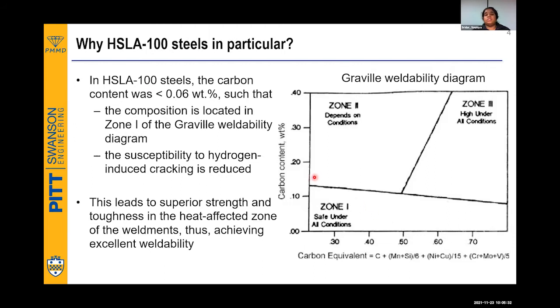And you see here, it's a plot between the carbon content and the carbon equivalent, which is calculated using this formula. It's completely empirical. If you see here, there are three zones. If your composition is in zone 1, then it is going to be safe under all conditions. Zone 2, it may fail or may not fail. Zone 3 is going to fail without any doubt. So we have to choose a carbon composition and a carbon equivalent such that the weldability is always restricted to zone 1. So that is the reason why this carbon content has been chosen.